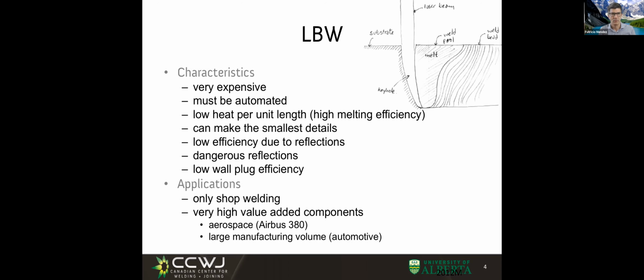But in addition, isn't it crazy that we're trying to put energy into a weld, and the weld is a mirror, and what we're using is light? We're trying to put all this energy in the form of light onto something that is the best possible reflector. So lots of the energy bounces out of the weld. It's the energy that, when it bounces back, can fry your laser or can cause you bad injuries.